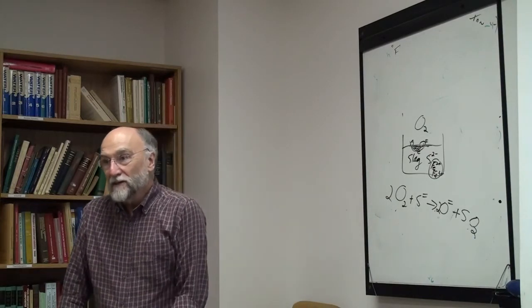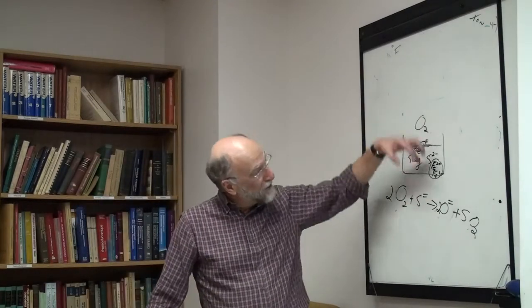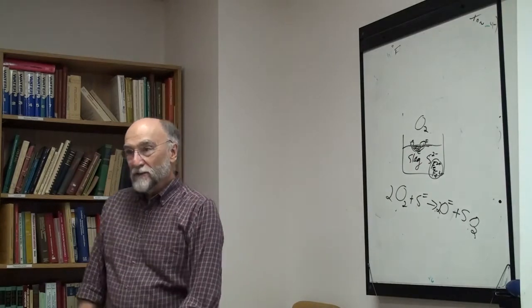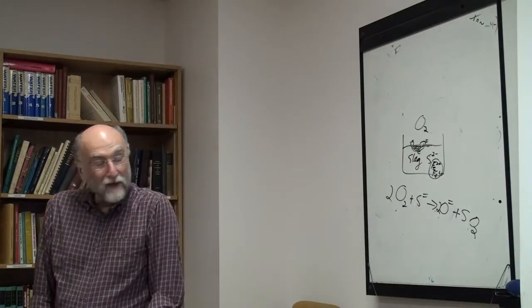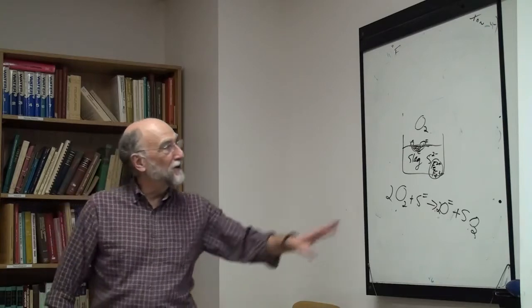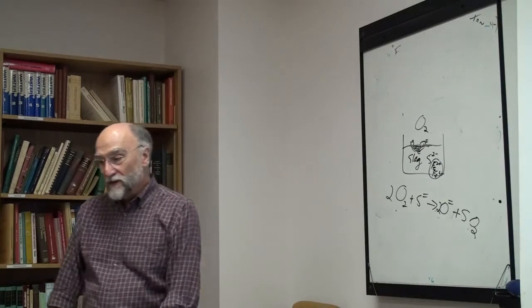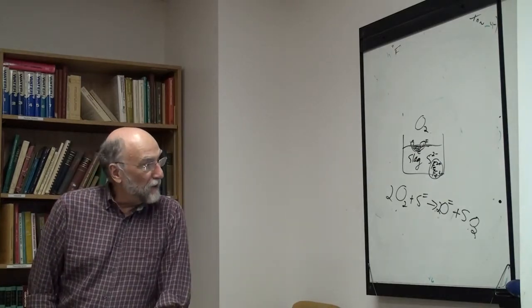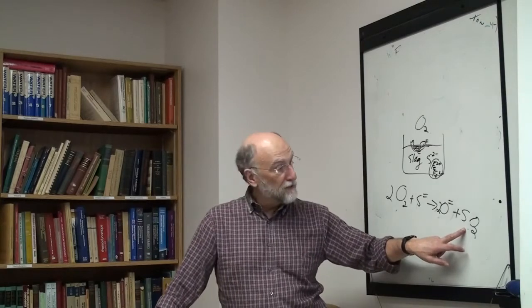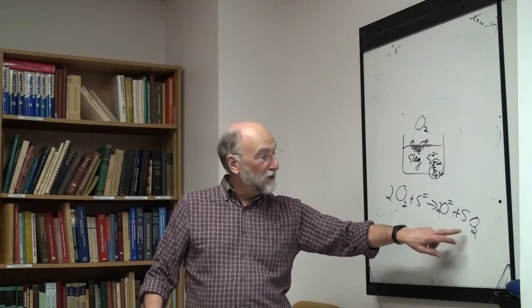Because you're forming sulfate. Rather than forming SO2, I was forming SO4, which stayed in the slag as sulfate ions. The solution to that, I don't know whether anybody implemented it, is this: you're putting the slags out in the atmosphere, and while they're cooling down, they're forming a lot of polluting SO2. You want to stop that as far as possible until the thing cools down. The way to do it is not to lower the oxygen pressure, but to increase the oxygen pressure.